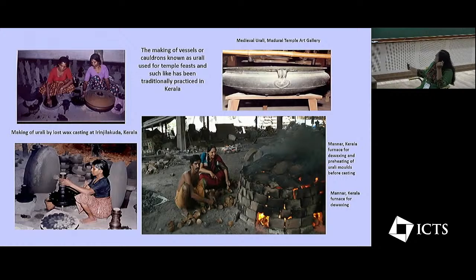And here you also see, of course, this was me there some years ago. Many of these processes, unfortunately, are dying out, but still, anyway, we have to document what we can. And here you see this huge furnace, which is used for dewaxing the mold and also for preheating, because that's also an important step. Once you have dewaxed the mold, got rid of the wax, before you pour the metal in, you must do the preheating so that the mold and the crucible are at about the same temperature, so that when you pour the metal in, you don't get a sort of explosion because the mold can crack and so on.